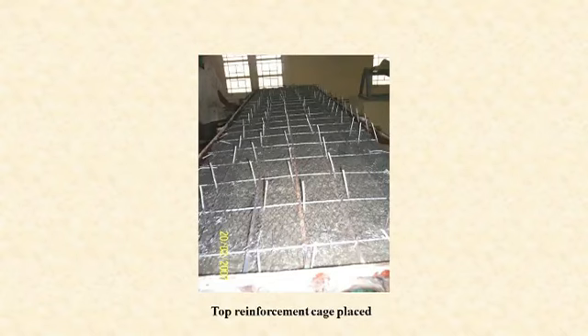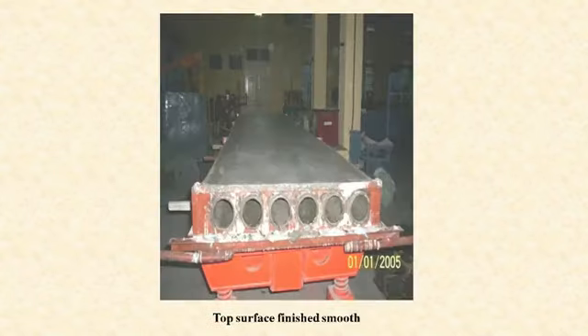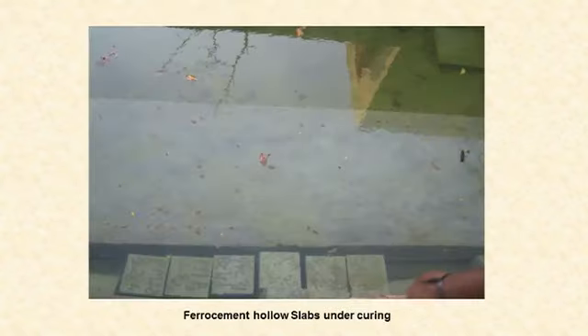And the top reinforcement cage was placed over, and the stirrups were hooked over the skeletal steel on top. Another layer of cement mortar was spread, and it was finished smooth. Efficient compaction was achieved by vibration over the table vibrator.